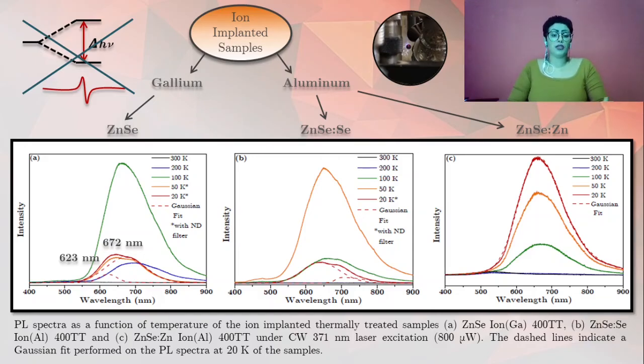In the PL measurements for the ZnSe sample implanted with gallium, it's possible to identify two bands with the Gaussian fit of the PL spectrum measured at 20 Kelvin. While for the ZnSe:Se sample, also implanted with aluminum, it's possible to identify only a broad luminescence band dominant in the spectrum.